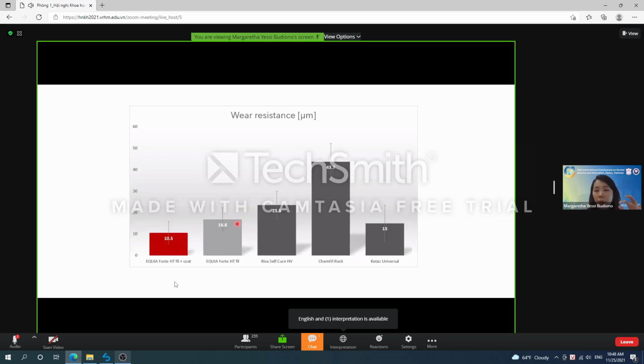And this is why using Equia Forte HT with the coat can increase the wear resistance significantly. So here in this chart, the lower the number is actually the better. We can see here with Equia Forte HT used together with the coat, the wear resistance is much higher than the wear resistance of the restorative material alone. But of course, if you want to use Equia Forte HT alone without the coat, you can do that. And it still has very good wear resistance compared to conventional GICs. But please remember that our goal as clinicians, we don't only want to fill in the cavity, right? But we also want to make sure that our restoration can last as long as possible so that we can reduce the repeat restoration cycle. So this is why we keep recommending doctors or clinicians to use the restorative material together with the coating agent.